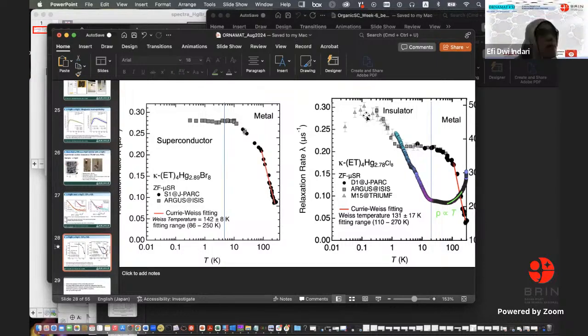It's not long range order because we don't see muon spin precession. So maybe it's consistent with not a triangular lattice. If it's a triangular lattice, we would see only ferromagnetic spin fluctuations, and we'd never see the decreasing of the relaxation rate. Yeah, hopefully like that.